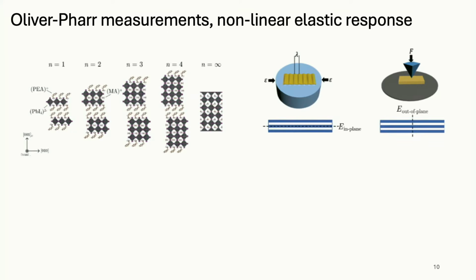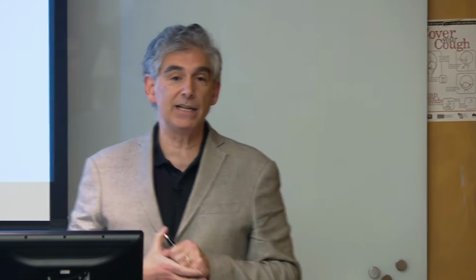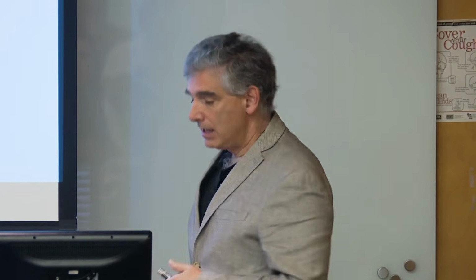So there are 2 kinds of tests that we like to do. One is to take the hybrid perovskite material and exfoliate it so it's thin, put it on a stretched rubber sheet, and then let the sheet contract, and note at what point you get a wrinkling instability, and this can give you a measure of the in-plane Young's modulus. And the other thing that's important to do is nano indentation, where you can take note of the relationship between the force applied to the tip and the amount of penetration into the material, and that gives you a readout on the out-of-plane elastic modulus.